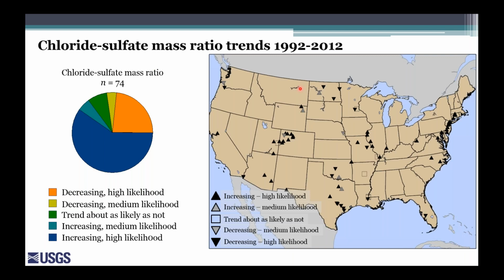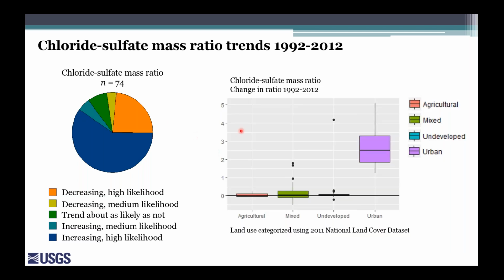Okay, so now we'll look at the trends in the chloride to sulfate mass ratio. The map and the pie chart are similar to what we saw for the chloride concentration trend analysis, but they focus on the chloride to sulfate mass ratio results instead. And in this case, approximately 2/3 of the sites included in the analysis showed some evidence for increasing chloride to sulfate mass ratio, as indicated by the blue colors. And similar to the chloride concentration trend analysis, we found that urban streams had very large increases in chloride to sulfate mass ratio between 1992 and 2012, while the other land use types had mostly small and inconsistent trends overall.